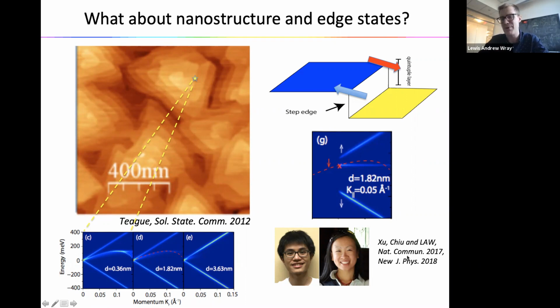We had a paper a couple of years ago in which we explored these for the edge state scenario, and found that generically you expect the in-gap states to also have a weird topological character, where they're quasi one-dimensional states that are spin polarized and that have a momentum energy dispersion that connects to the Dirac point of the material. And so you can imagine them as, if you put a chemical potential near this Dirac point, these edge states will carry electrons with one spin in one direction and with the other spin in the opposite direction. They potentially can be an interesting kind of nanoscale wire.